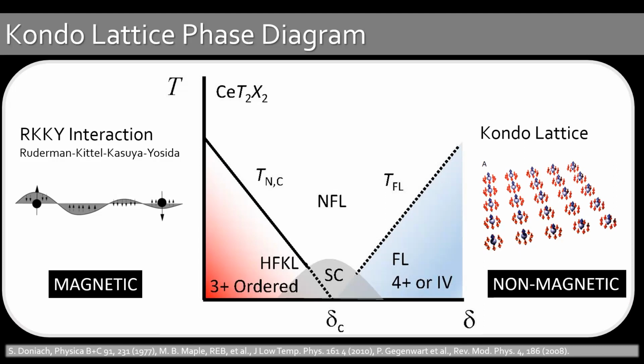On the other hand, the Kondo lattice, there's so much to say about it, I won't try to say much of it at all, except that what happens here is that the conduction electrons like to screen away this local moment. And it will tend to give us a non-magnetic ground state. And if you tune these the right way, they're in competition with each other. You can give a quantum critical point. Sometimes there's superconductivity, and then the emergence of this weakly magnetic Fermi liquid.